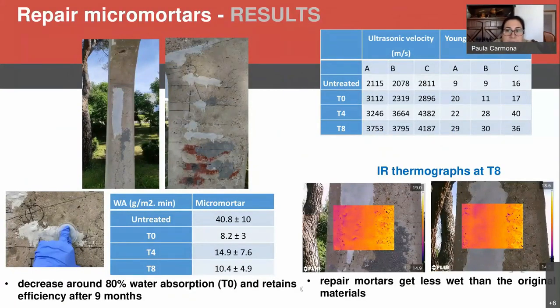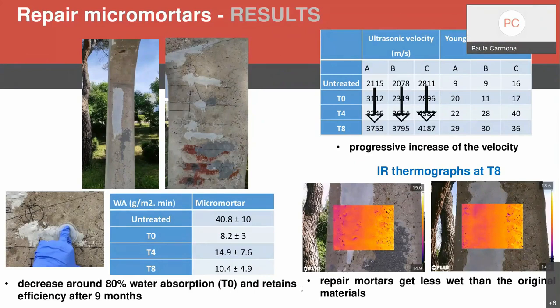You can see here the results of the validation of this micromortar. The results were also, like the previous treatments, very successful. Not only did the mortars increase the ultrasonic velocity, you can see here how the ultrasonic velocity increased after applying the treatments. T0 represents 1 month after the application of the treatments, T4 5 months, and T8 9 months after the application of the treatments. And you can see here also how the micromortar reduced the water absorption by around 80%, and retains this efficiency after 9 months.